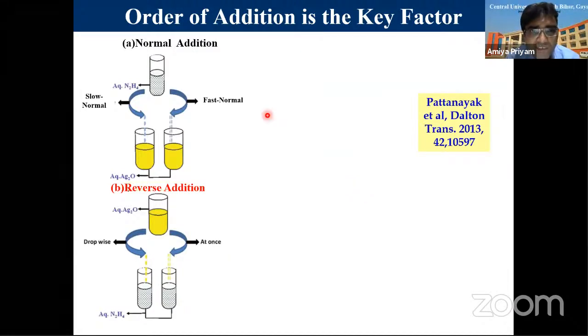So what we found is that order of addition is very important in this case, and it matters a lot whether you are adding reducing agent to the silver oxide or your silver oxide is added to this reducing agent. Depending on that, we evolved a methodology. We call it normal addition when we add the hydrazine to the Ag2O, silver oxide. Within this, you can have two types of methods: single shot addition, very fast, and slow, where you add it dropwise. So we call it slow normal and fast normal.